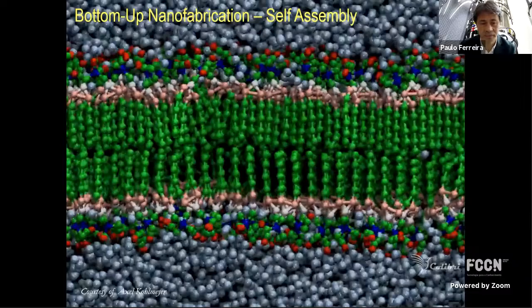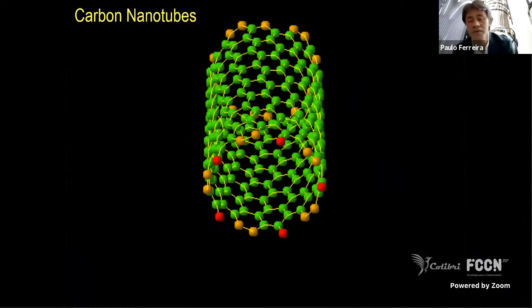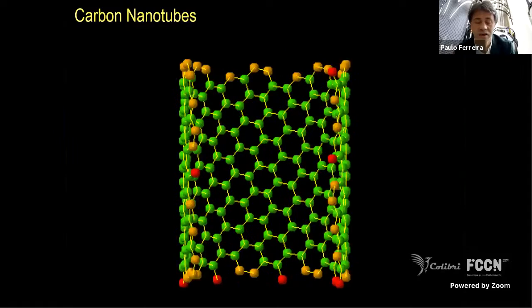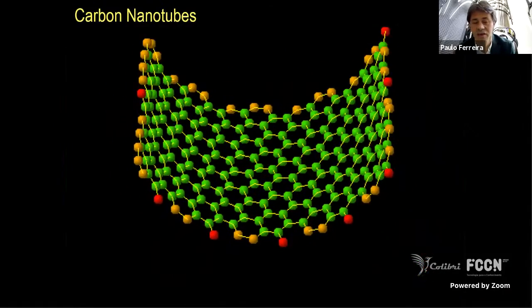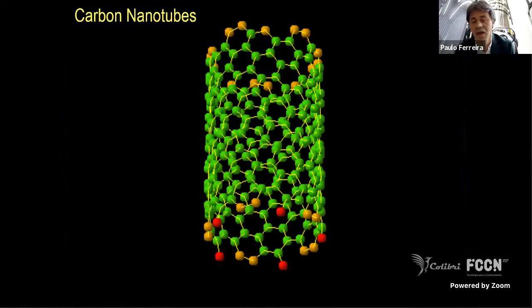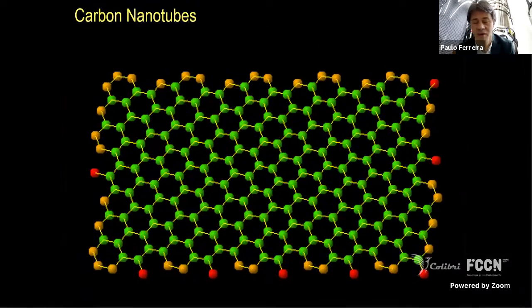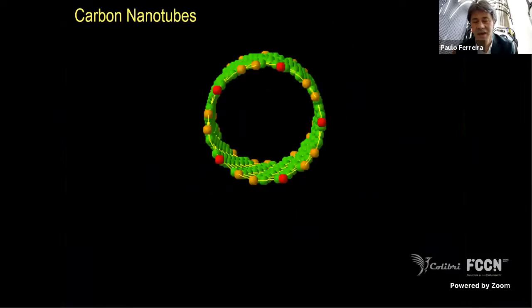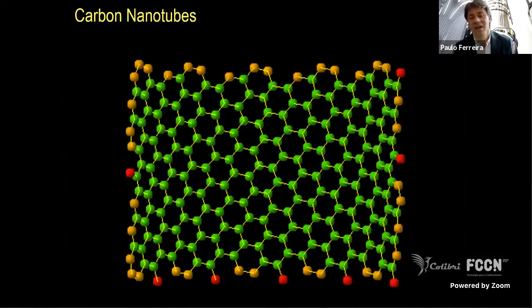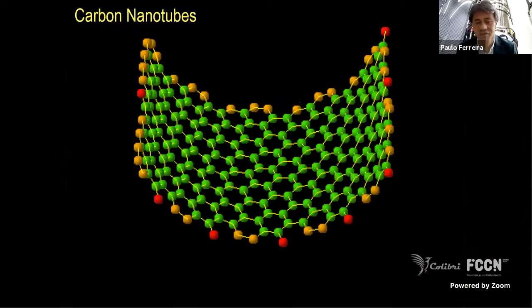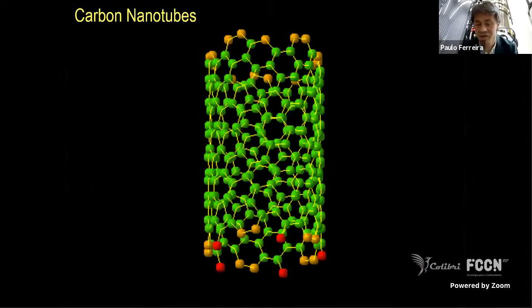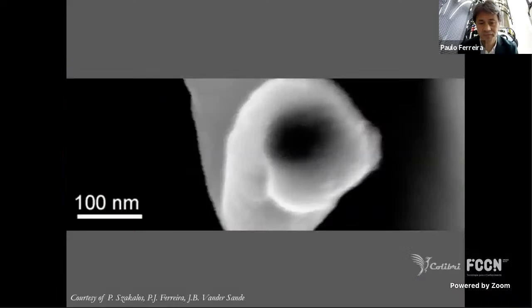nature actually works. Another example is, of course, the carbon nanotubes. Under certain conditions of pressure and temperature, these carbon atoms fold into these tubes, which are materials with very interesting properties. But again, you don't need any kind of intervention. It's basically self-assembly into these kinds of structures, provided you get the right temperature and pressure. And here's an image from the scanning electron microscope. You're looking edge on into the length of one of these tubes. You can see the opening, and they are in fact quite real.